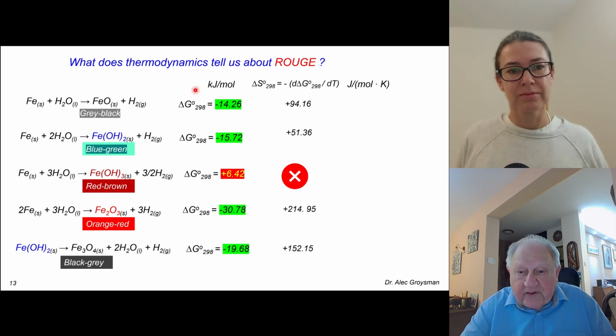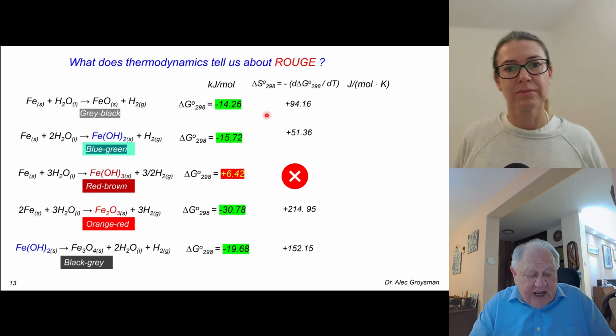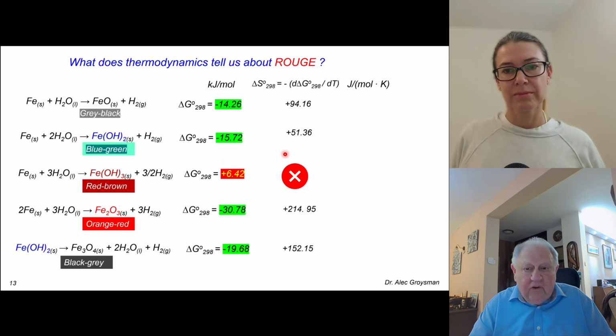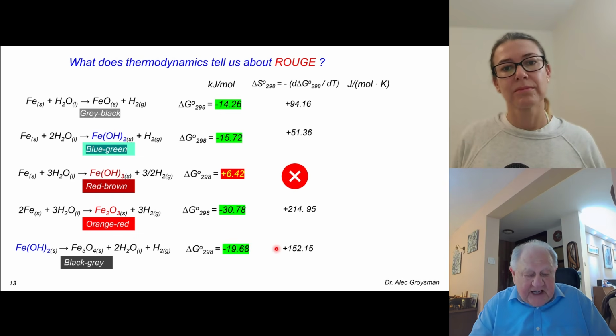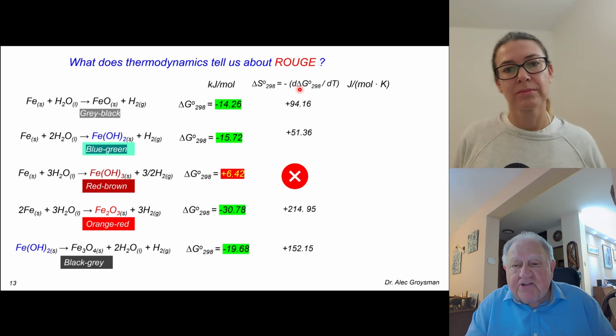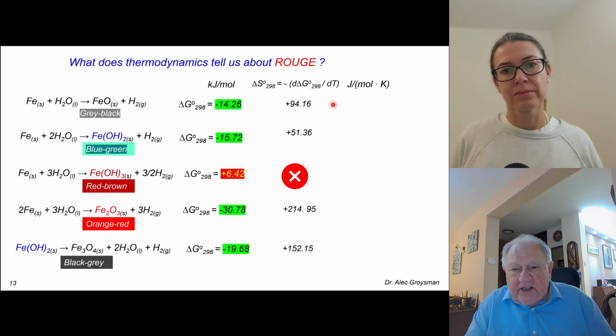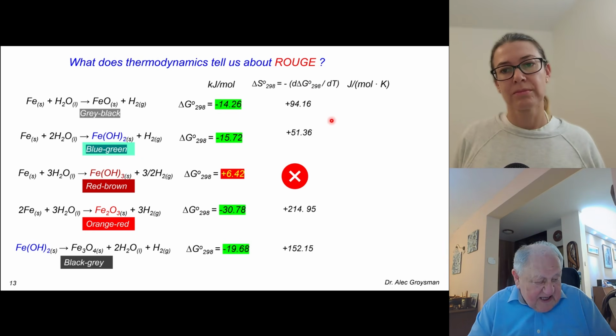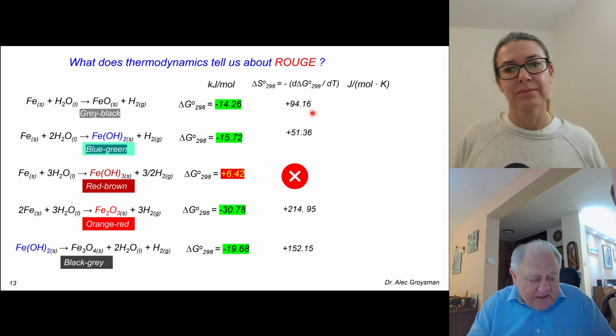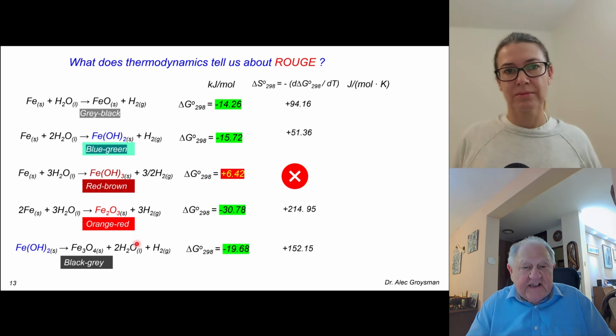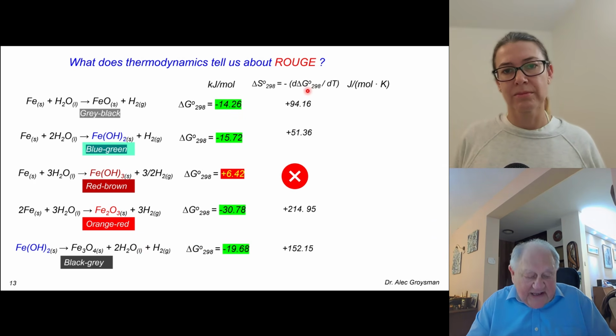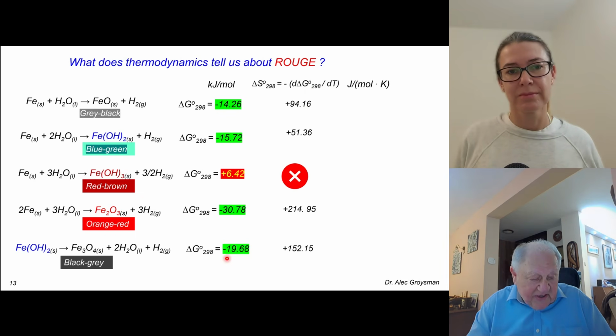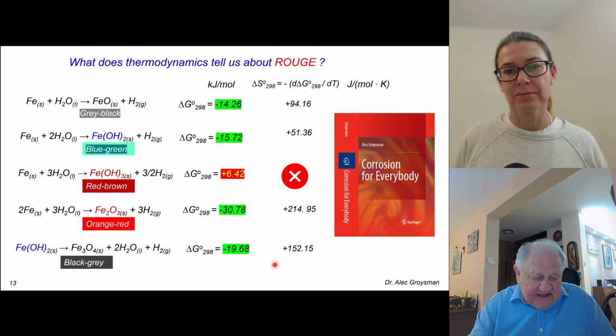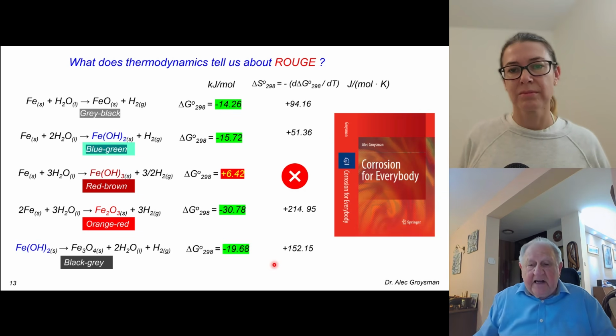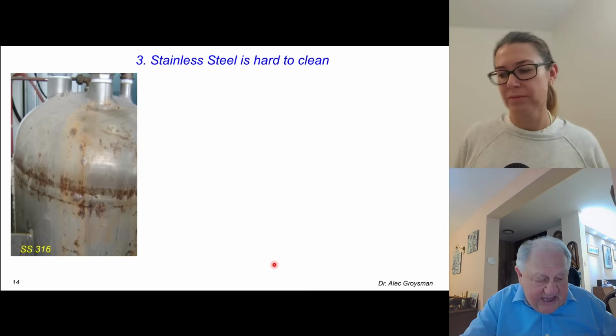We can go further and calculate the entropy change for each reaction. For all 4 reactions, we see entropy change is positive. Entropy change is minus the differential of delta G by dT, the temperature. This means that increase of temperature results in increase of tendency of the corrosion reaction, as delta G is lower with increase of temperature. Wonderful picture, correct? You may find all such calculations and reasoning in my first book, Corrosion for Everybody.